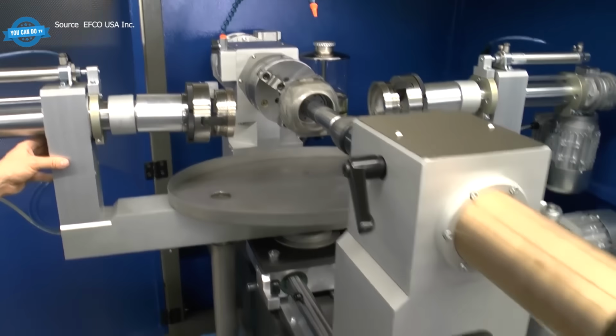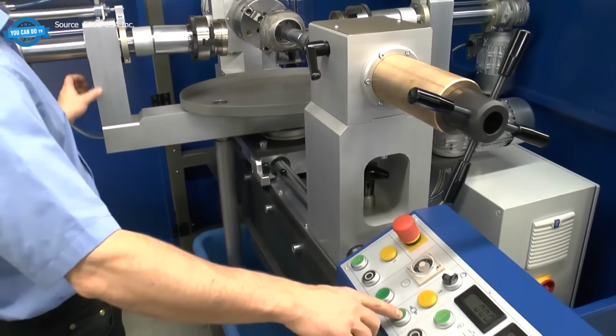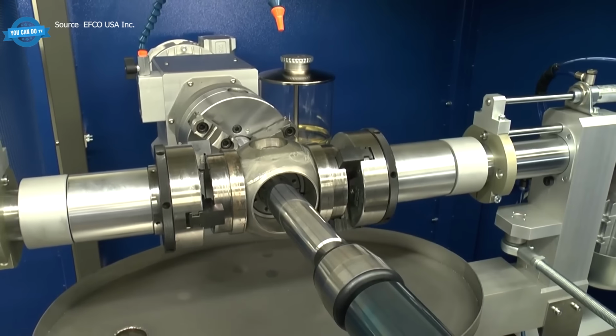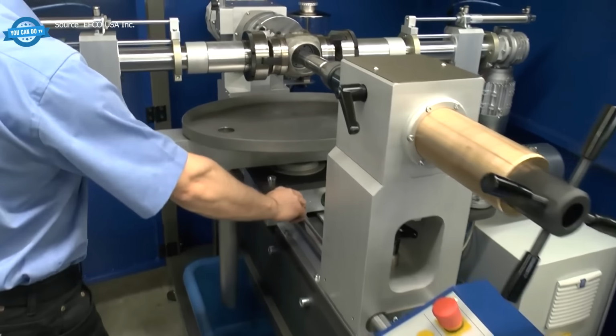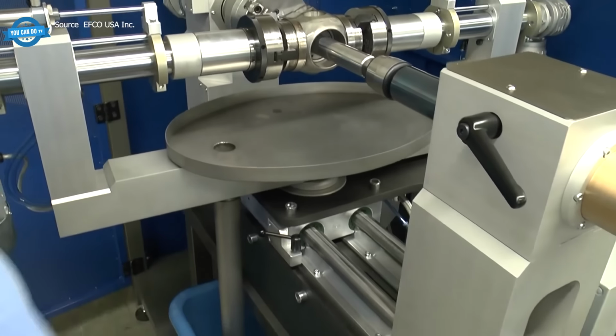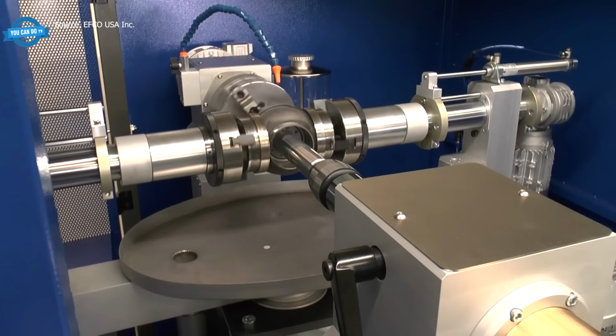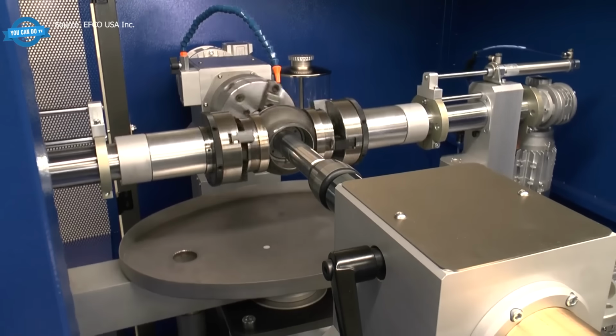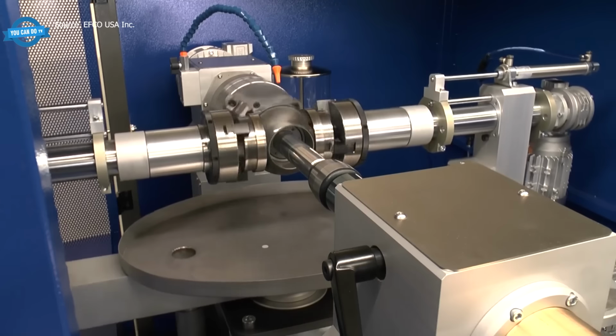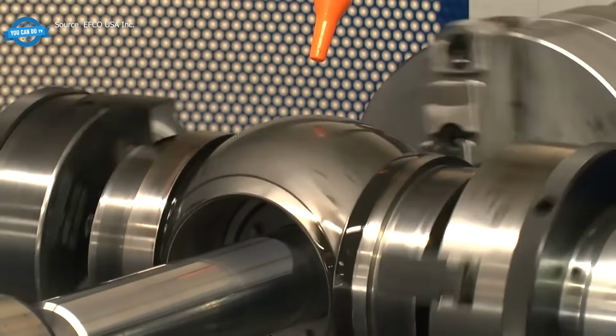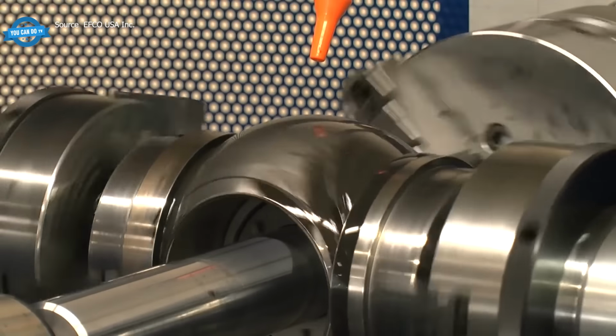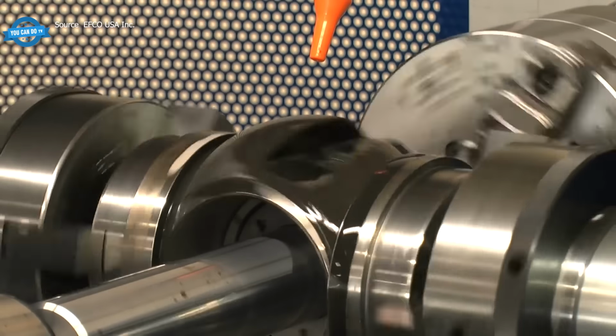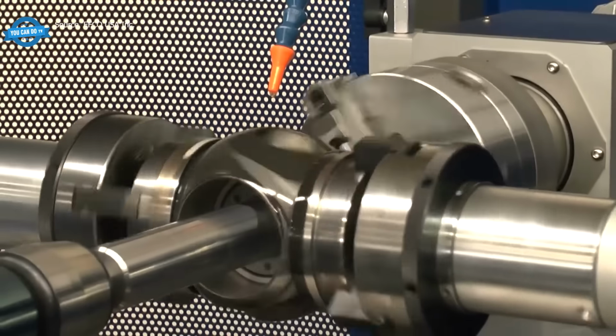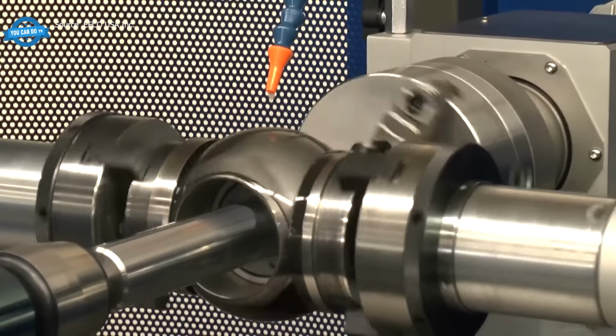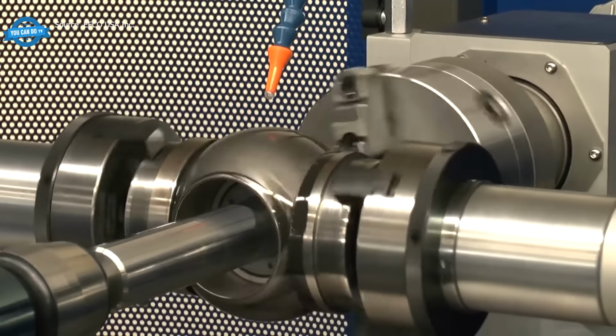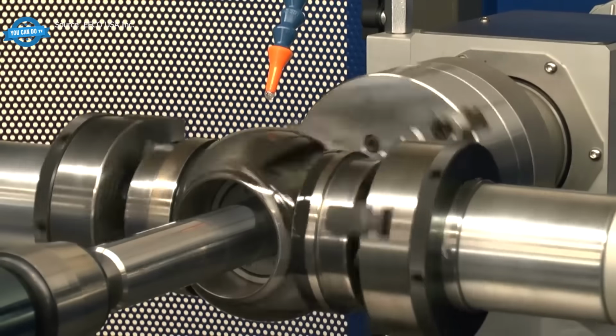After the cycle, the ball emerges mirror-polished. A leak test with colored fluid confirms zero seepage once the seats are refitted. Surface roughness measurement on a digital profilometer puts numbers behind that visual result. Average roughness as low as 0.05 micrometers, with maximum profile height under 0.5 micrometers. Tolerances fine enough that the human eye alone could never certify them.